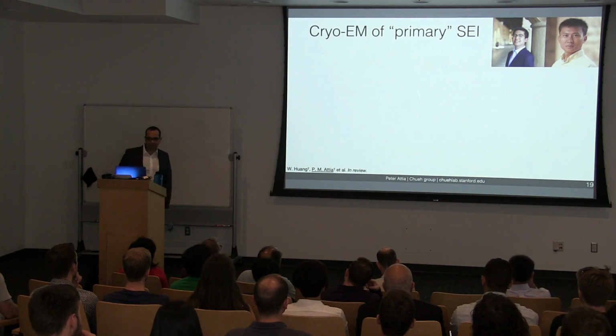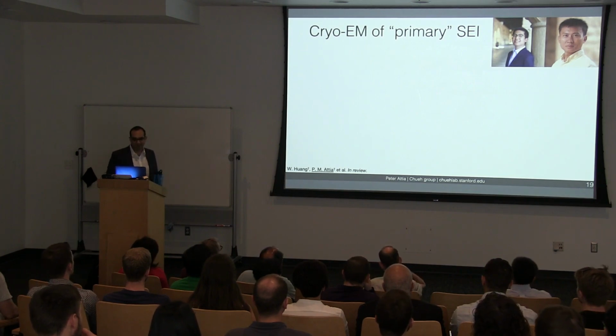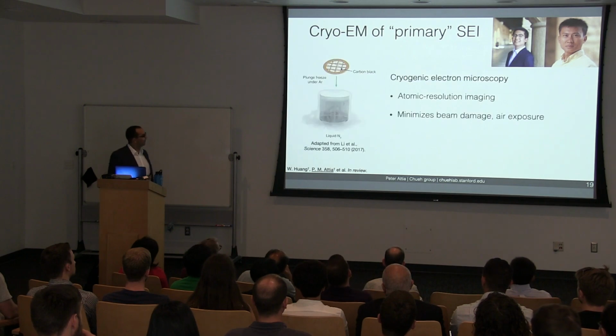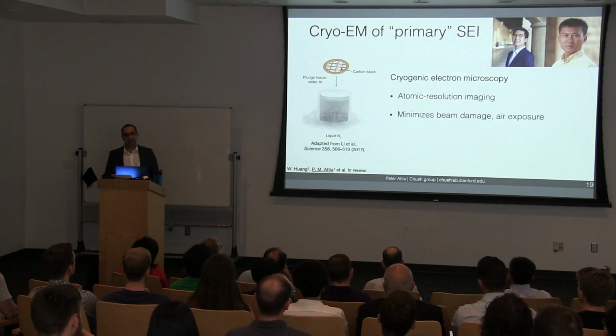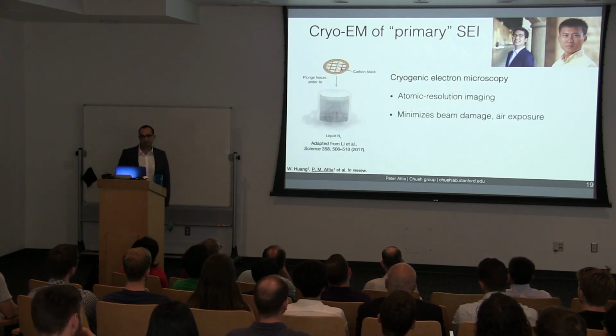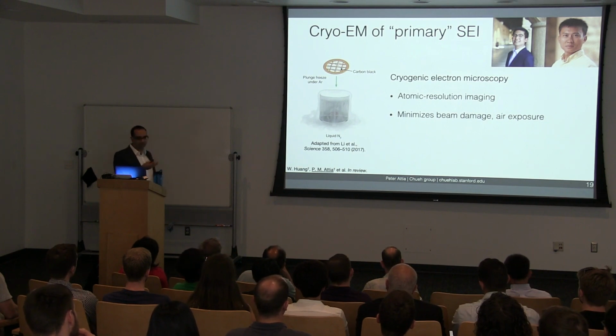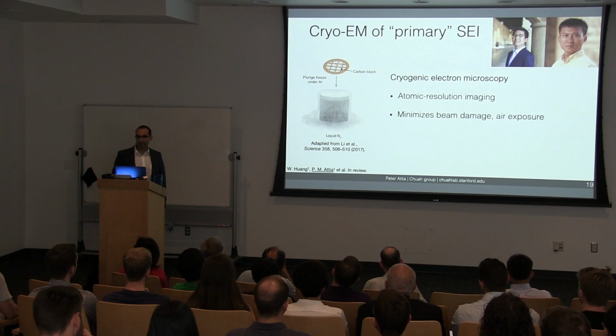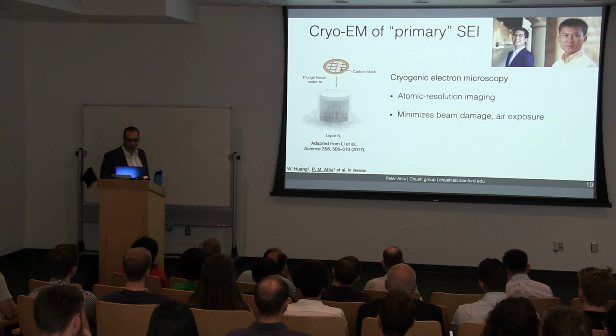So we started by applying cryogenic electron microscopy, or Cryo-EM for short, to understand the local structure of the SEI. Applying this technique to batteries was really pioneered by the Cui group here at Stanford, and for this project, we worked closely with Will. Cryo-EM enables atomic resolution imaging with minimal beam damage and air exposure. The idea is that if we freeze the sample, we can prevent further reaction with air and use lower beam doses to achieve comparable images. This is critical because, again, SEI is traditionally very difficult to characterize.